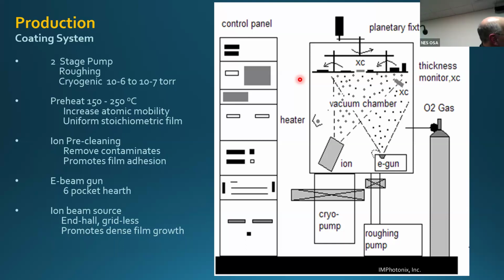Okay, so this is a typical physical vapor deposition system. It's a vacuum system. We use a cryo pump and a mechanical pump. I was talking to a gentleman earlier where they still use a diffusion pump in the college, and some of the problems that creates. But the cryo pump gets down to a very low vacuum, 10 to the minus 6, 10 to the minus 7 torr, which you need when you're depositing films. Because if you're going to deposit tantalum pentoxide, you don't want to deposit it in nitrogen or carbon or anything else that's floating in the air. You want a good vacuum so you get good stoichiometric properties of the film. So a good low vacuum is essential.